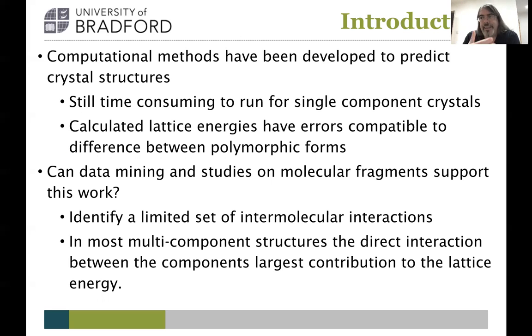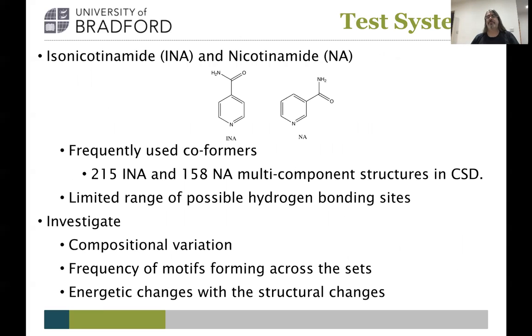And indeed, if we look into lattice energies of multi-component crystals, very often the strongest interaction present is the one between the two different species, and that's contributing significantly to the overall lattice energy. So rather than calculating the whole lattice energy, do we just need to look at one or two dominant strength interactions to push forward the predictive method?